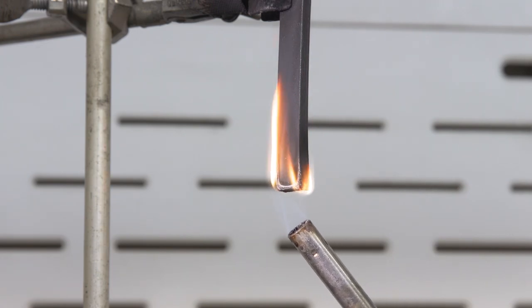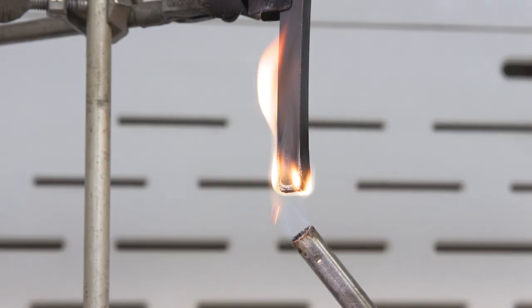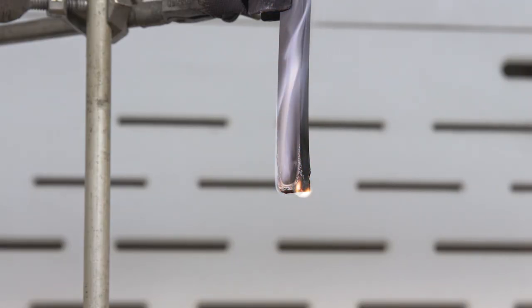So there's a number of different test procedures, but the amount of flame retardant and thermal runaway mitigation material we can put in a non-cellular material is a factor of 100 more than you can put in a cellular material. So again, ratcheting up that level of safety that's available for an engineer's potting and encapsulation. Well, there's a draw towards foams because of the density reasons. As I mentioned earlier, engineers in batteries get judged off their gravimetrics at the end of the day, and people care about how many watt-hours per kilogram you packaged. And so having a material that promises a lower density per cc is often the first place engineers jump.